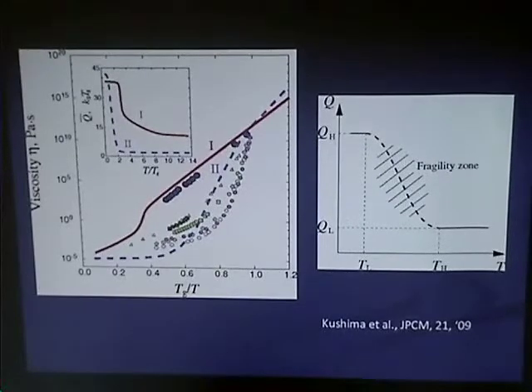I'll talk about how that's done, and it's related to a question you mentioned about finite size effects. We find, and we'd like to understand, that we see apparent Arrhenius behavior as a robust thing in the relaxation there, and that plateau value is tunable with film thickness - very sensitive to the film thickness. Other people have recently seen this by very independent methods.